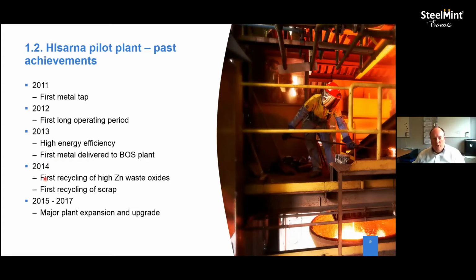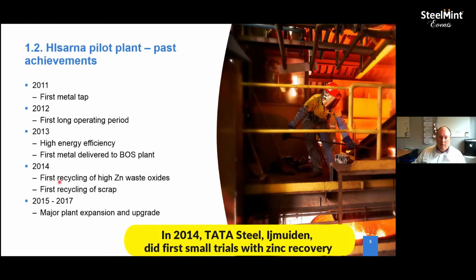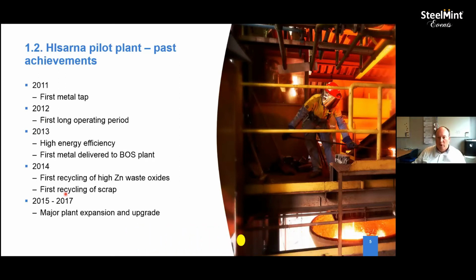And in 2014, we did the first small-scale trials with zinc recovery and also with the addition of scrap. And then between 2015 and 17, we did a major plant expansion, where the biggest changes really were that the off-gas duct had a design flaw in it. So the whole off-gas duct had to be rebuilt to remove that design flaw. And until then, because we need our coal and our iron ore to be able to go through pneumatic injection systems, it needs to be dry and of a certain particle size. That was all done off-site, the screening and the drying, and to make sure that we could run longer without creating a logistical nightmare, we also built a coal grinding and drying facility and an iron ore drying facility, so we could create a continuous feed for much longer periods of time.